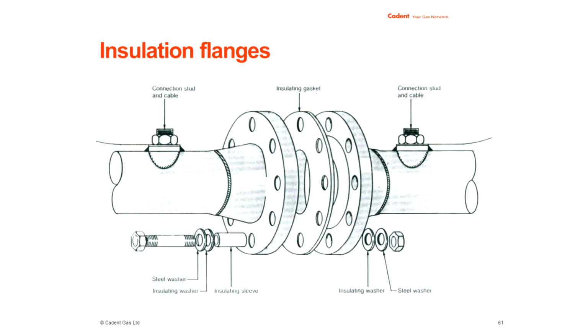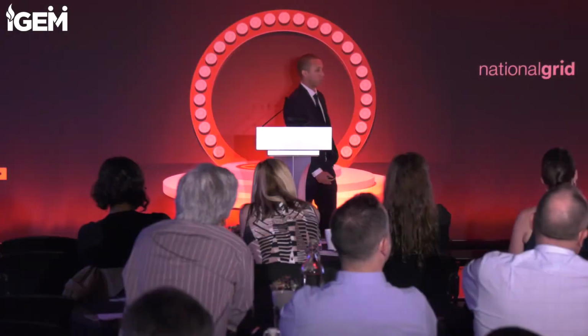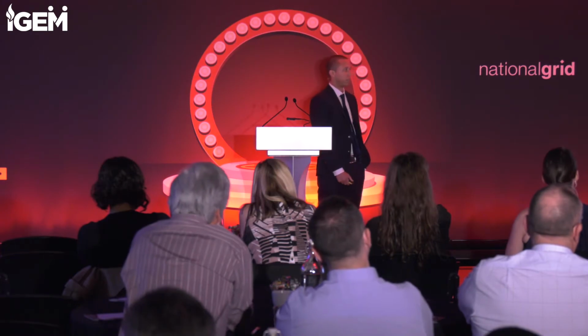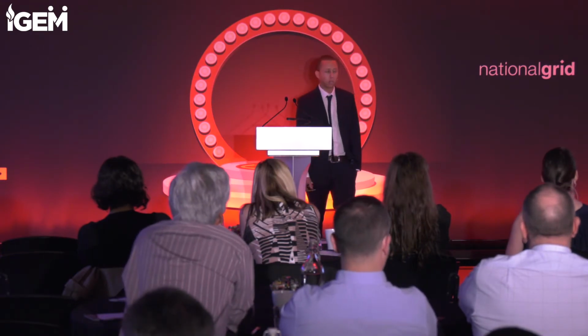Now these flanges should be above ground, but unfortunately our iron and steel interfaces tend to be below ground a lot of the time. So they've caused us a lot of issues over the years, as the insulation flanges have become conductive as they've had moisture ingress, and we've lost all isolation between the steel and the cast iron.